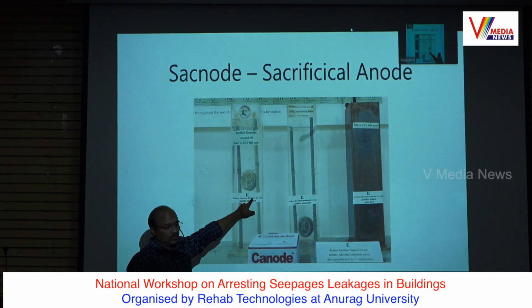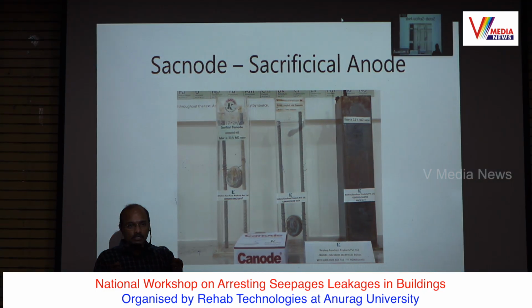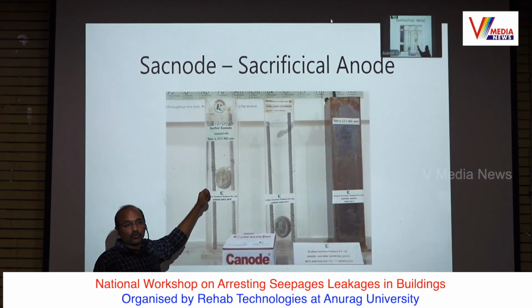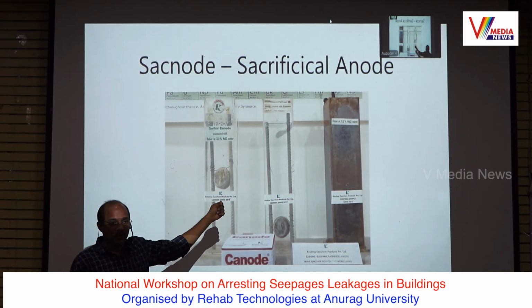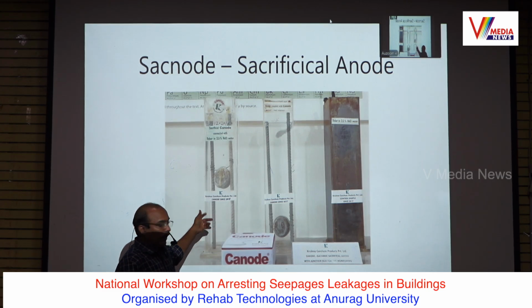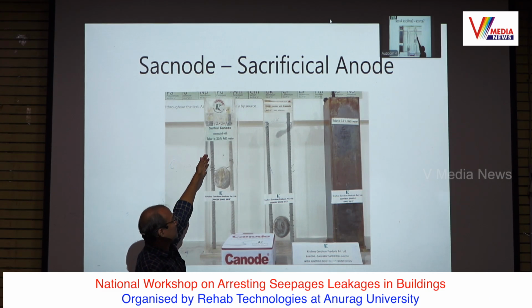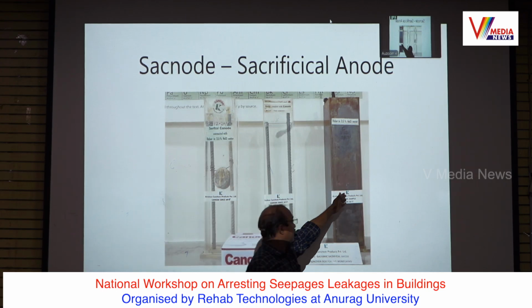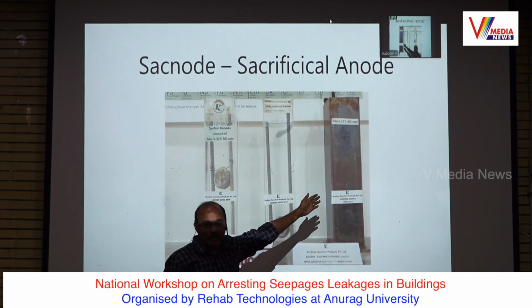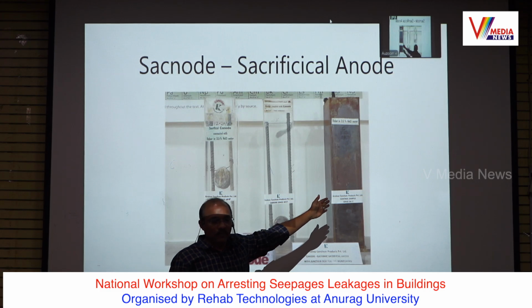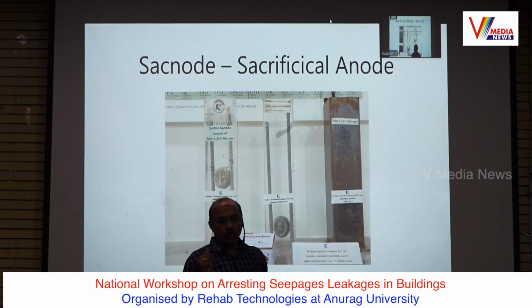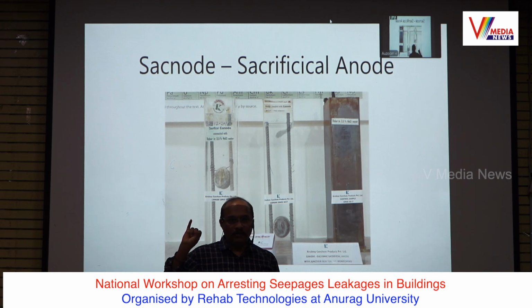To the two steel bars, we have sacrificial zinc anodes connected, exposed to 3.5% sodium chloride solution, which is a seawater kind of environment. When you expose this, the steel starts getting corroded, and you leave it. The steel bar, which was like that in 2016, when I went there a couple of weeks back, has become something like this. In exposure, steel will corrode so much that nothing will be left for the structure. So in highly corrosive areas, I am talking about industrial areas, areas with very severe ground pollution, and areas nearby lake beds. I think most of the lakes are polluted right now.